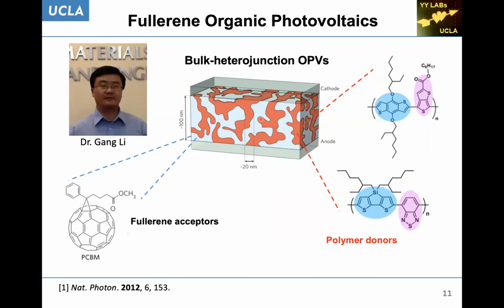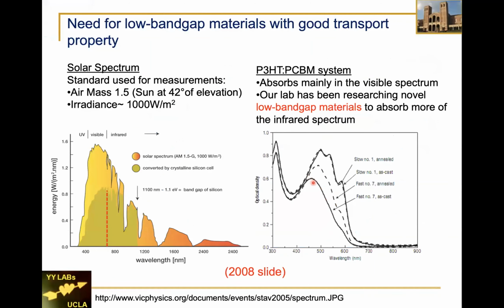He found that by so-called slow growth, with exactly the same material, you can see when Dr. Gang Li slowly extends the drying time, the absorption gets better and better. And then you can see this pi electron interaction start to show up when we dry the film, instead of a few seconds, in a few minutes. The longest time you dry, I think, is 30 minutes. So with that, you can see that the absorption is increased. As I mentioned to you, when the absorption increases, the photocurrent increases. So that's a very good observation, and that's established.